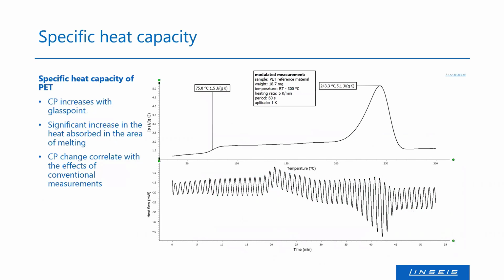Okay, now here's again an example from myself, and I hope you can also see this is the same result as the literature CP value before. And what can we see here? The CP increases with the glass point at around 75 degrees, so 70 to 80 normally for PET. And there's no recrystallization because it's non-reversible. And then we will find the big melting peak.